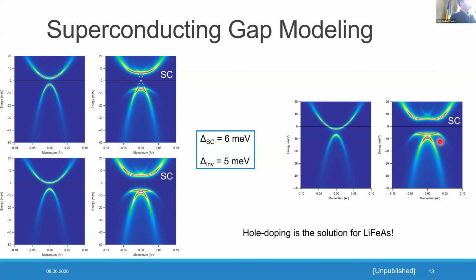And in the case of lithium iron arsenide, it's also true. So of course it's possible what you are saying, but we measured a lot of samples, and there were a lot of extra precautions, like not putting it into the air because lithium reacts with air very strongly. We were seeing with LiFeAs also that the band structure was quite quickly deteriorating with time.